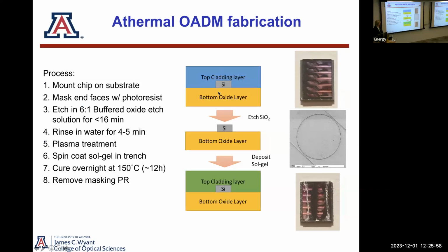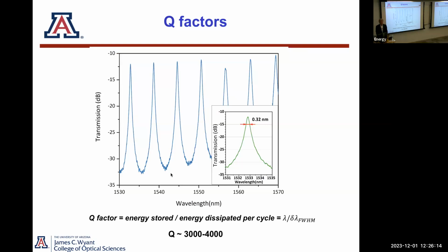This was our received chip. We took the top cladding off. This is a wet etch process. We've now developed a dry etch process for doing this, and then putting a top cladding layer on that would basically make the chip less temperature sensitive. And we did all that.